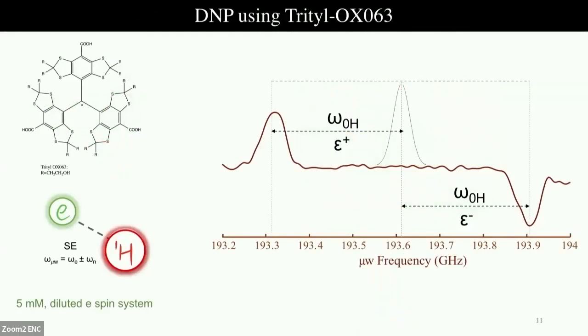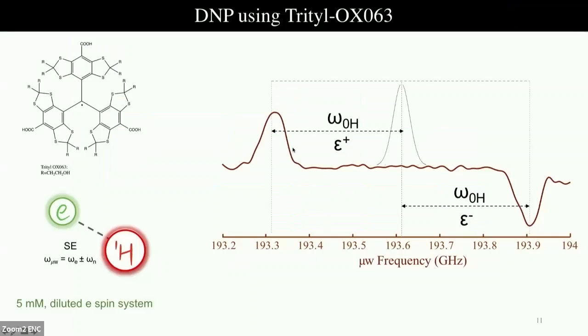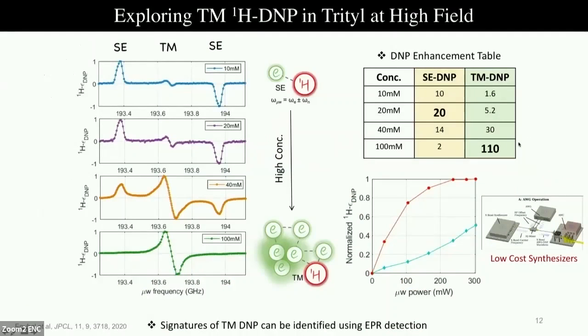So in our study, we made use of trityl, which has a narrow line. If the trityl is too dilute, then we would only have solid effect enhancement for the trityl. It could be a zero quantum or double quantum solid effect DNP. But if we have concentrated trityl, as we increase the concentration, what we see, apart from the solid effect, is DNP coming right at the center of the trityl line. We didn't have any other option for what this could be, so we assigned this to be thermal mixing DNP. And as we increase the concentration, this thermal mixing DNP in trityl enhances and the solid effect goes down.